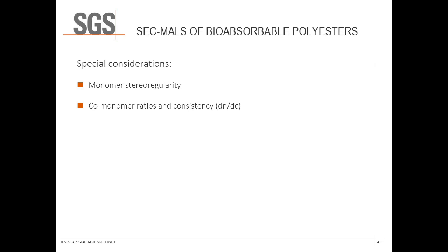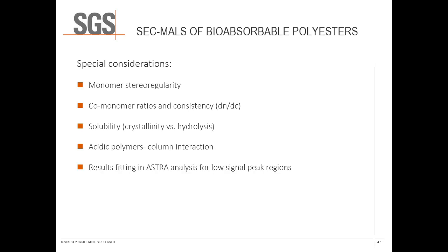Some polyester samples are crystalline and require heat to dissolve, but may also be subject to hydrolysis if heated excessively. Organic soluble acidic polymers have a propensity for column interactions which must be inhibited by the addition of acidic mobile phase modifiers. Finally, the results fitting feature of the Astra software allows for the inclusion of data where inadequate light scattering signal leads to unrealistic calculated molar mass values.